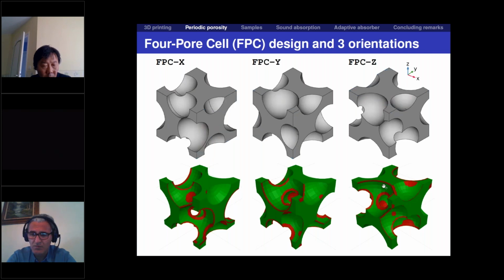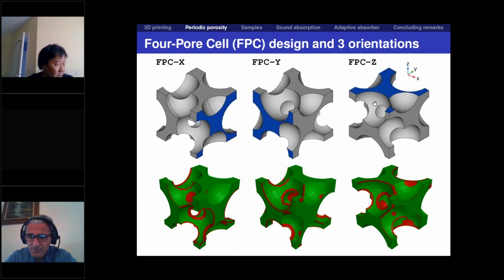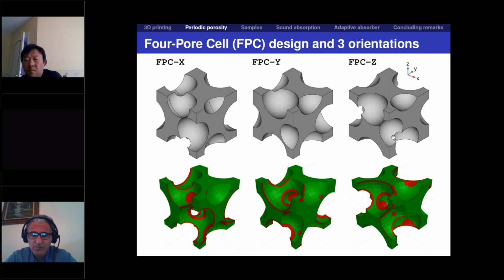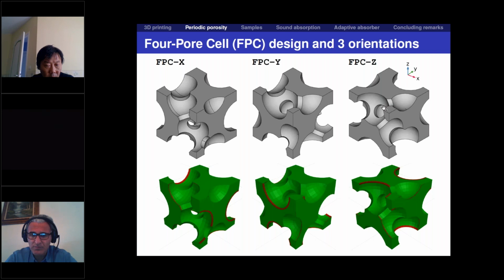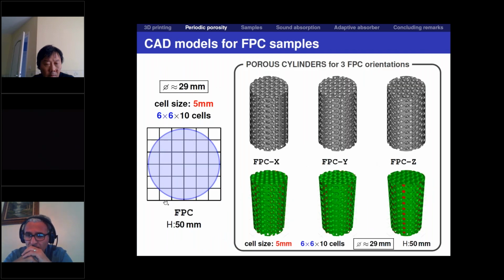So in order to avoid this, I decreased the diameter of all the pores by 10%, and then I used the original diameters of the windows linking these pores for, let's say, cylindrical channels that link the pores that were previously linked by the windows. And now you see that this geometry can be correctly 3D printed, and obviously we put an additional unit cell above, so these red areas will vanish completely, and we generate this kind of three-dimensional array, 6 × 6 × 10, so the height of the array is 50 millimeters, and we cut out cylindrical samples with a diameter of, let's say, 29 millimeters, the diameter of our impedance tube.